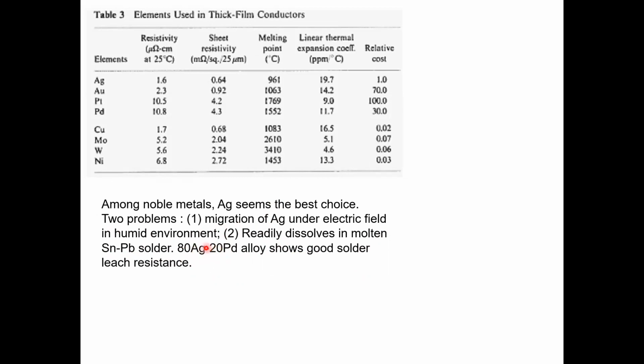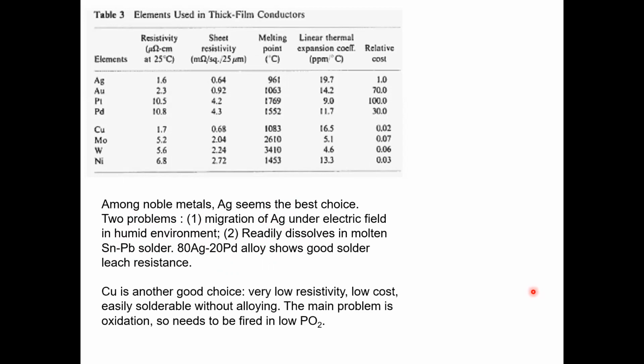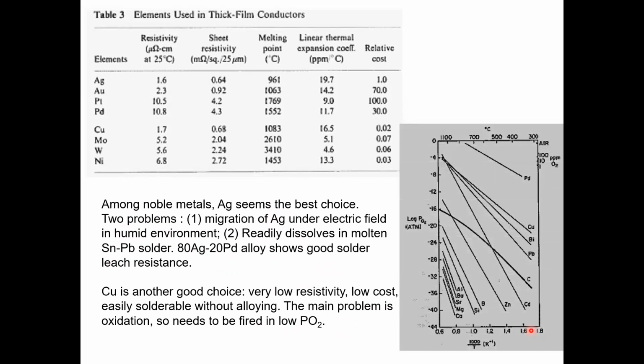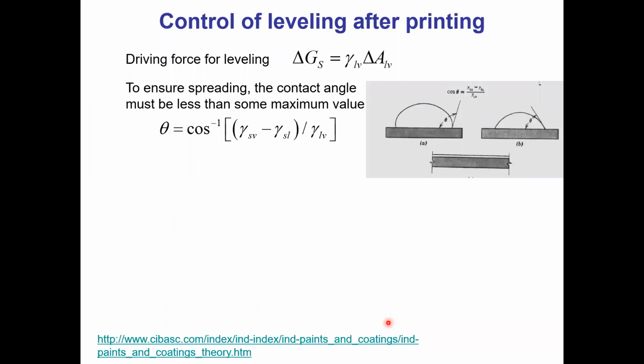So even though you use the silver-palladium alloy as the conductor, it has better resistance in terms of dissolution of the solder material, less solubility of this into the alloy as opposed to pure silver. The problem with copper, though, is the oxidation problem, and you have to be careful about the Ellingham-type diagram where if you cross this boundary in terms of oxygen content, depending on the temperature, most of this metal, including copper, will oxidize. So that's one of the reasons why copper is not such an attractive electrode material, but silver, gold, and platinum are.